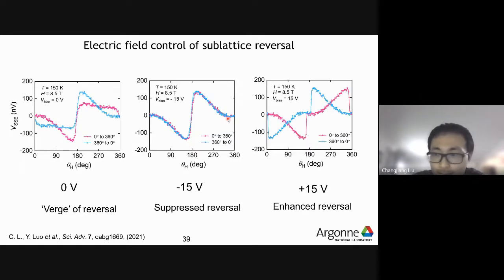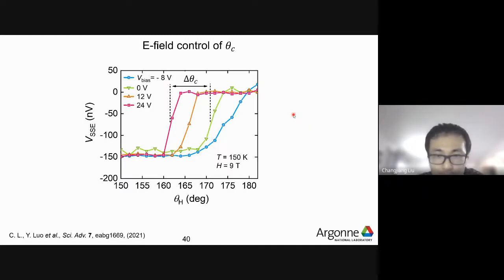Now, when we apply a positive gate voltage of 15 volt, you see a sudden jump happening, and the curve is no longer continuous and no longer reversible. Rather, you see a hysteretic behavior. This is just like the measurement done at a high field above the spin flop transition. However, here we are doing the measurement at the same magnetic field. The only difference is the voltage applied across the thickness of chromium oxide.